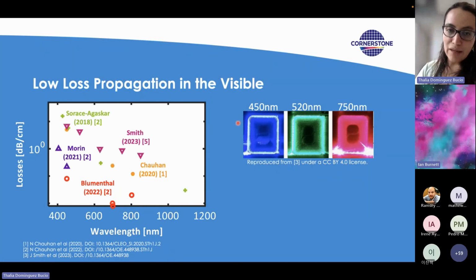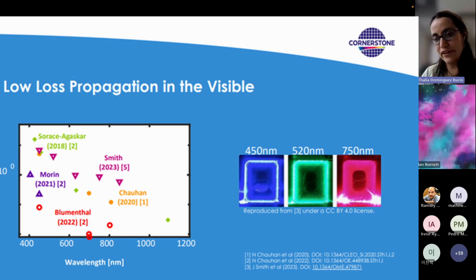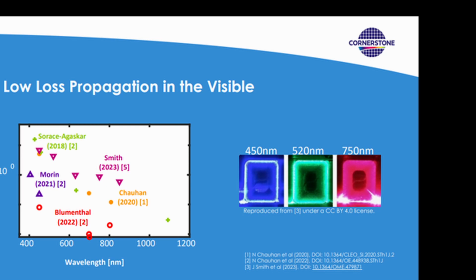So here I have two examples of waveguides in the visible. These ones were fabricated in standard foundry services with thicknesses of 150 nanometers. And you can see that you can transmit the light very well, but you see some scattering. And of course, you see some losses because the light is not so intense. However, if you look at these low loss waveguides, which are fabricated with a thinner silicon nitride core, you will see that you can get very long spirals with a very good transmission of the light at 450 nanometers, which is the shorter part of the spectrum, and almost at 700 nanometers, which is the red part of the spectrum.